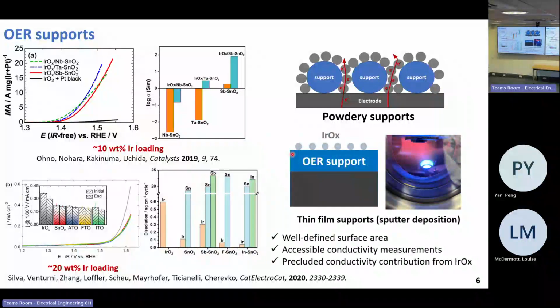As mentioned earlier, iridium oxide is still very conductive, and with these powdery samples, it's hard to exclude the conductivity contribution from iridium oxide. So in my project, I'm looking at thin films. I fabricated OER support into thin films for iridium to sit on, so we can get well-defined surface area of the support, and it's easier to measure the conductivity, as well as we can preclude the conductivity contribution from iridium oxide.